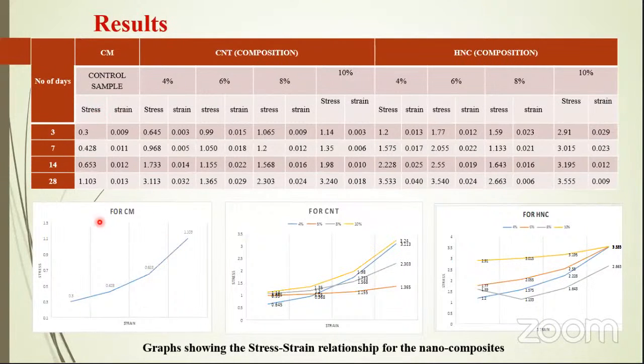And these are the results for the stress strain graphs that we have obtained. As you can see, for cement mortar, for all the days, the stress strain graph is gradually increasing. And even for different percentages here, there are 4, 6, 8 and 10 percentage graphs. The growth is more or less similar, except for this one, 6%, which is deviating from the other lines. And even here, the graph is more or less the same for all percentages, only it is changing for 8%. This change is attributed to human error either during loading or mixing or some calculations.